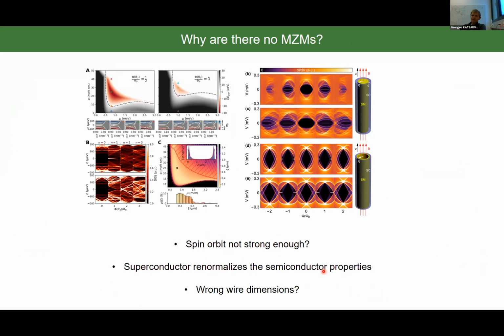And we have 3 possible explanations. The one question is: is the spin orbit not strong enough in our intrinsic nanowire? If you take a look at plot A, in order to reach the topological phase, your alpha, your spin orbit constant, needs to be higher than a certain value. So can it be that our nanowire has not strong enough spin orbit? Or can it be that it actually had strong enough spin orbit, but the superconductor has renormalized the semiconductor properties? Or have we simply used wrong wire dimensions?